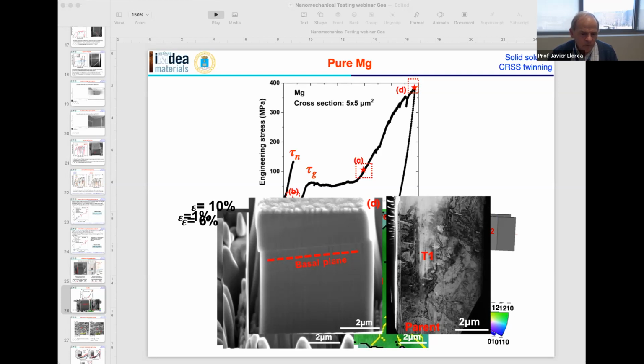So at point B, this is what you see. When you take a lamella and do transmission Kikuchi diffraction, you can see that this is the parent grain, but two twins have been nucleated in the upper part of the crystal. So this load drop was due to twin nucleation. Then you deform the crystal along this line and you go to point C. At point C, this is the shape of the pillar, at about 6% deformation. What you can see here is that the twins have grown. The two twin variants have grown and they occupy most of the pillar. So now your pillar has a completely different orientation. That was the original orientation of the pillar.